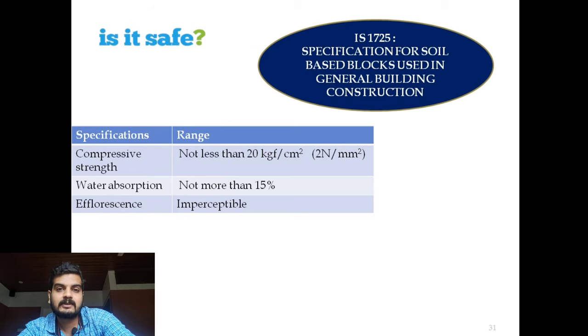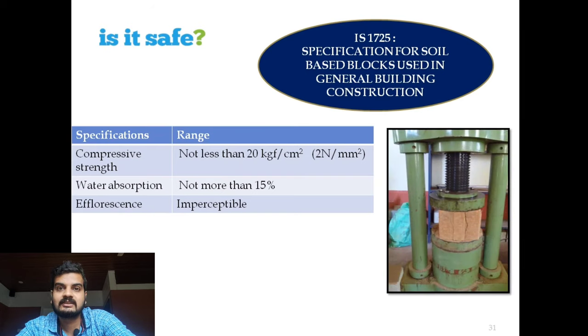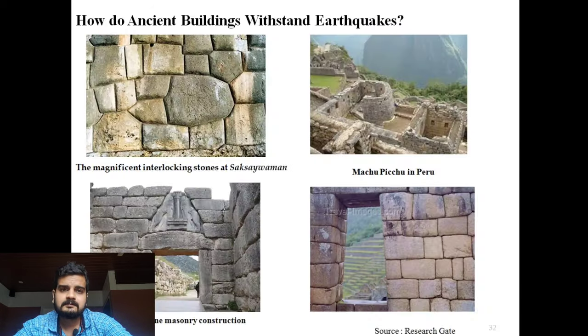And the compressive strength is more than 2 newton per mm square. When I tested around 150 bricks in the lab, the strength I got was around 2.2 to 4 newton per mm square. As we increase the curing days, you will get more strength. And the water absorption also is not more than 15%. These are the safety factors.